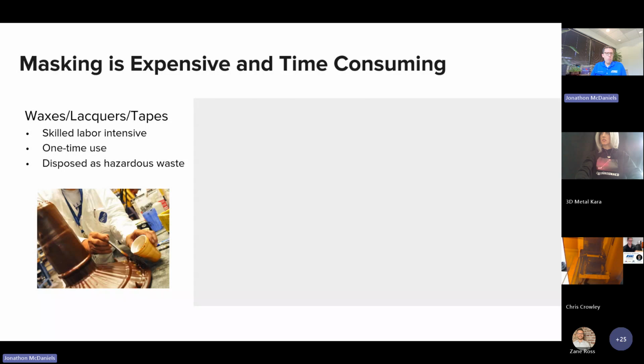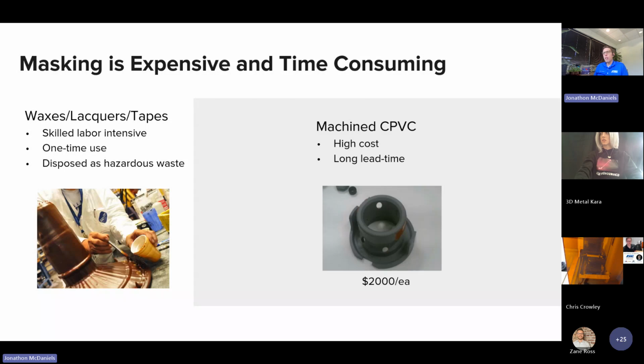And then even worse, that tape or that wax that you removed, if it's gone into a chrome electroplating process, it's disposed of as hazardous waste. So there's a lot of issues with waxes, lacquers, and tapes. Like I said, one of the more robust and repeatable methods that's sometimes used to alleviate this is machined CPVC.